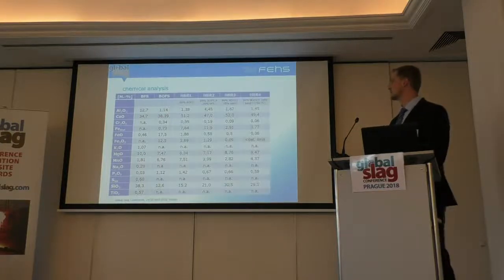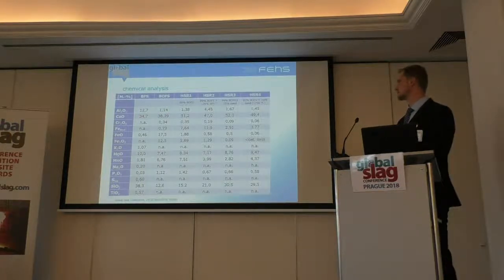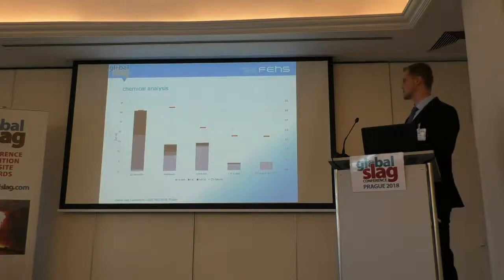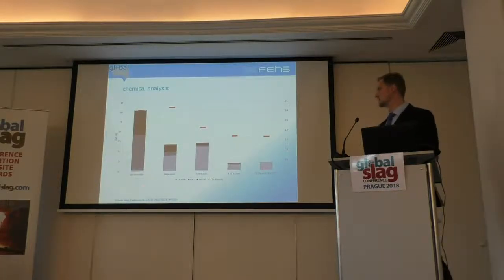When you're looking to the chemical analysis, it was typical BOF slag and the other one, the blast furnace slag, with iron oxide about 30% summarized, and we decrease this to nearly zero, the oxidic iron. I will show you in the next diagram. It looks like this, or it looks a little bit better.